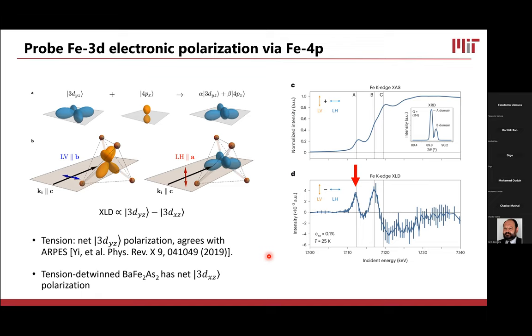Okay. So if you are above the nematic transition, then the 3d_xz and 3d_yz orbitals are degenerate. Even under zero strain, you'll end up seeing zero XLD signal. You'll see a large XAS signal, but no XLD. If you cool below the transition, you still don't see an XLD because you have an equal population of the two domains. But once you apply strain, then you're breaking the symmetry of the occupation, and then you'll see a net XLD signal. But am I hearing you say that the concern is around strain unequally tuning the absorptions of the two orbitals?